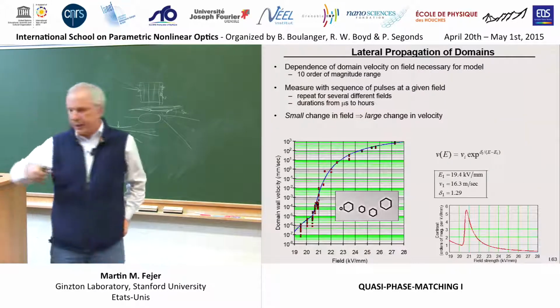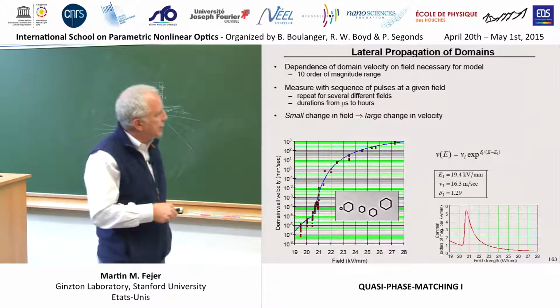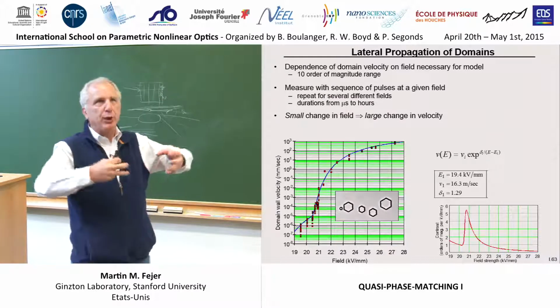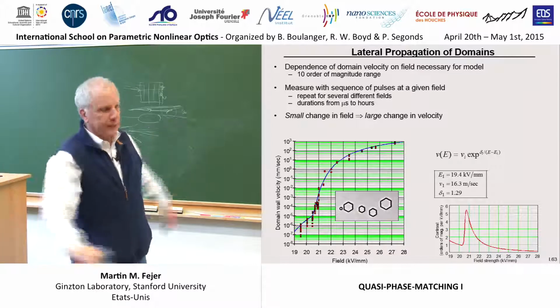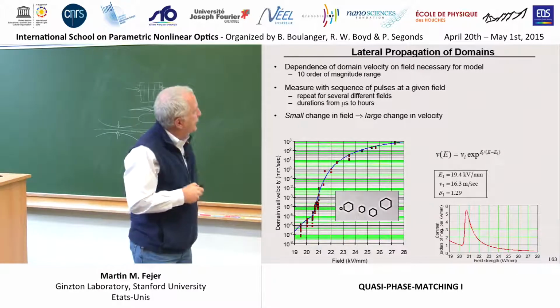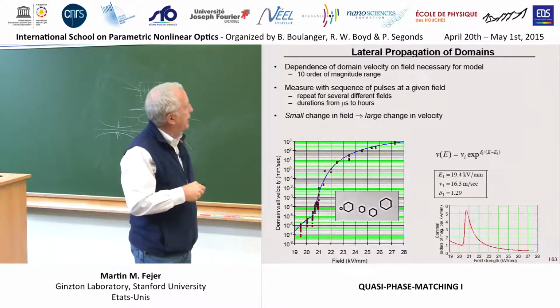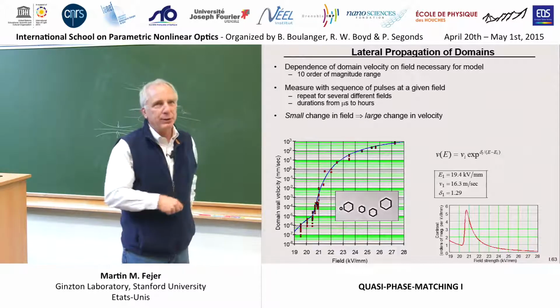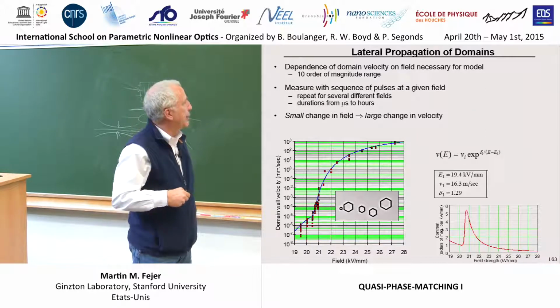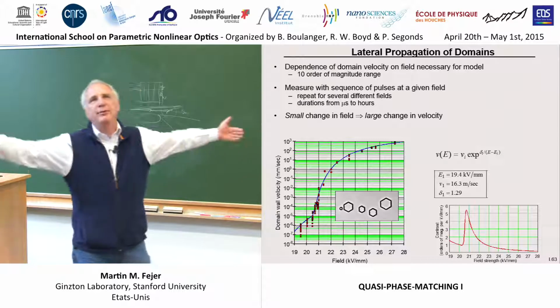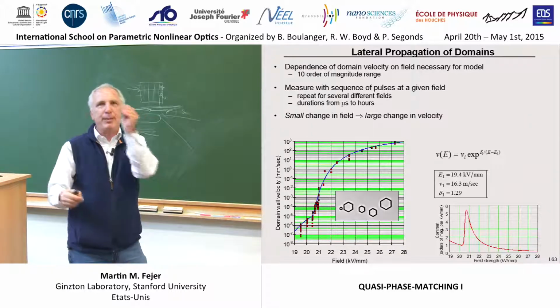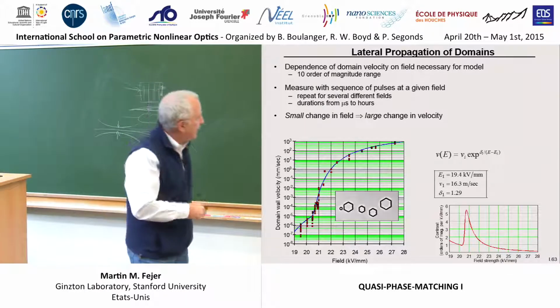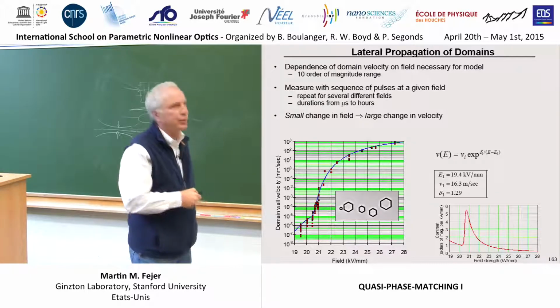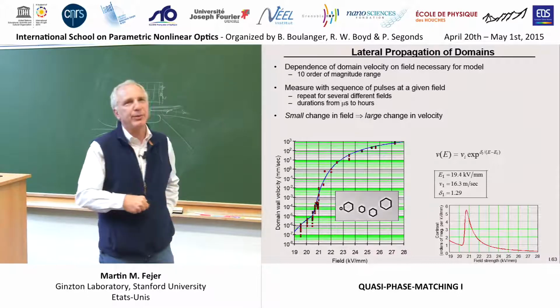And on an unpatterned wafer, you can just watch these spontaneously nucleated domains grow and look at how the size changes as a function of time. And if you look at this graph here, this is logarithmic, and it goes over 11 orders of magnitude. So this is 10 to the 3 millimeters per second, a meter per second velocity of these things that you're trying to pattern to micron accuracies. And this is 10 to the minus 11 meters per second. So this is 1/10 of an angstrom per second.